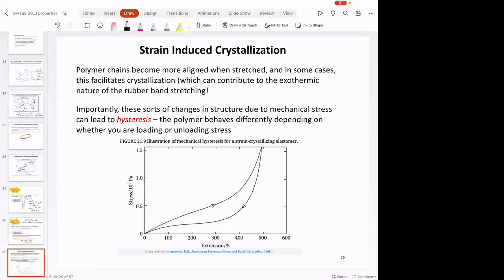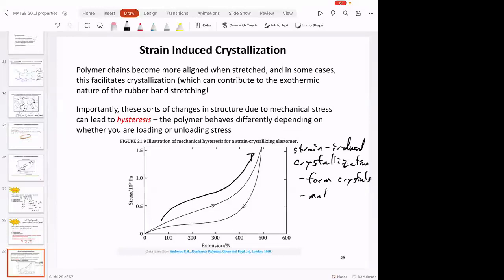So when you let go of the rubber band, what happens? So you stretched it here, you get strain-induced crystallization. You form crystals. Material gets stiffer. Notice this slope goes up, right? So if we look at the local modulus there, that's not the Young's modulus. Young's modulus only happens way down here. But if you look at the instantaneous or the local modulus, when that curve turns up, the material's getting stiffer because you're building in crystals as you strain it.